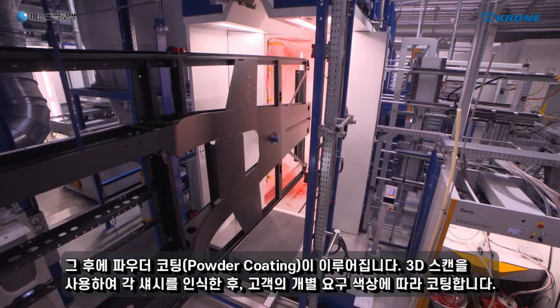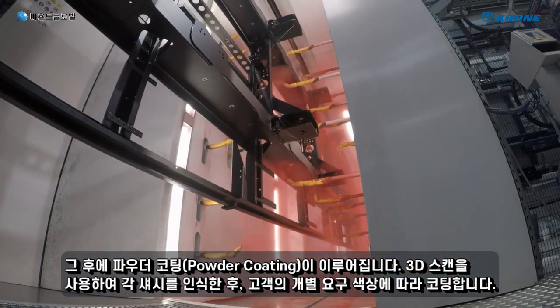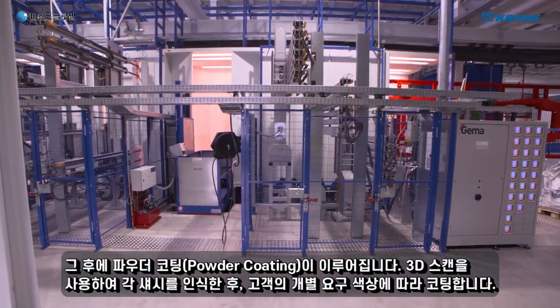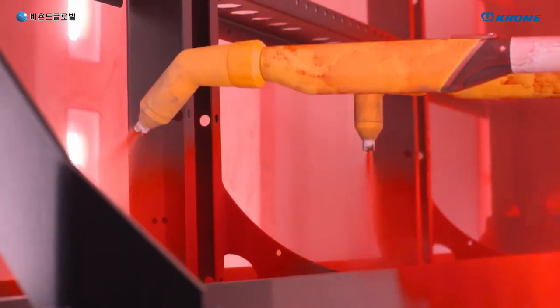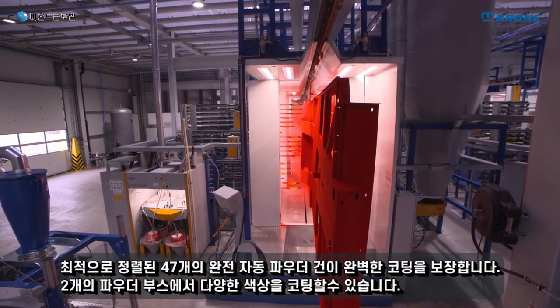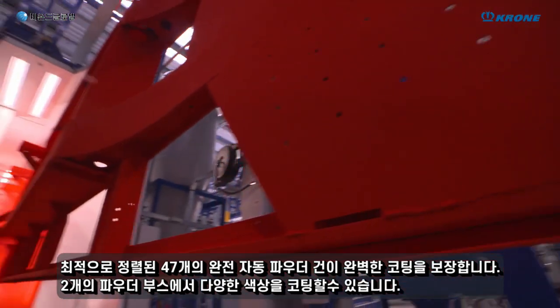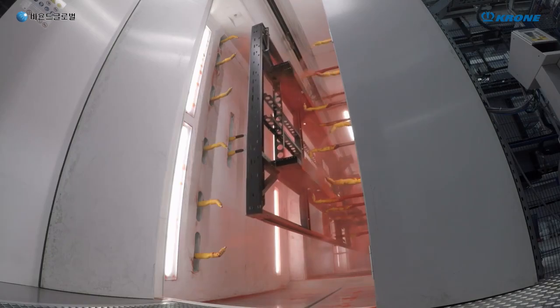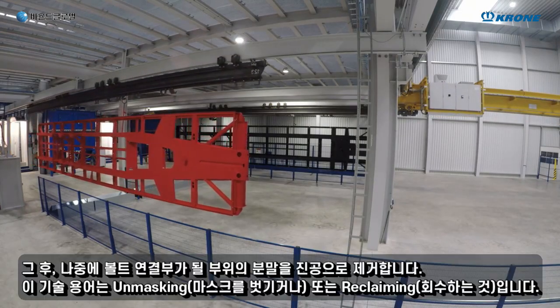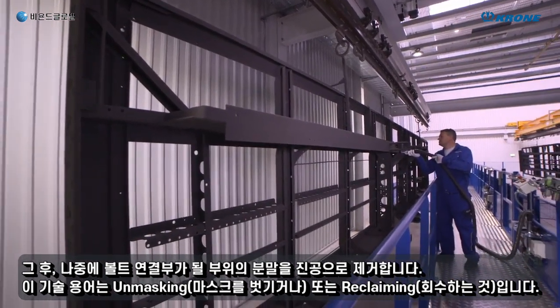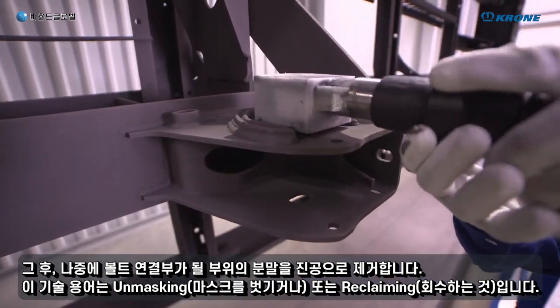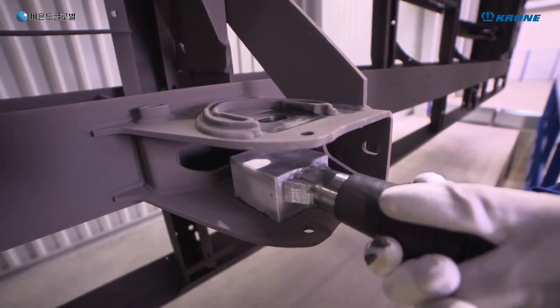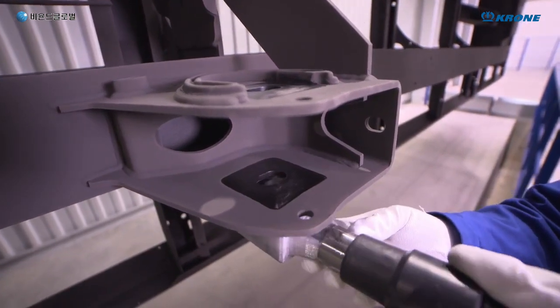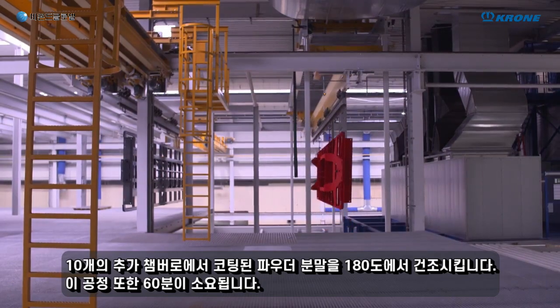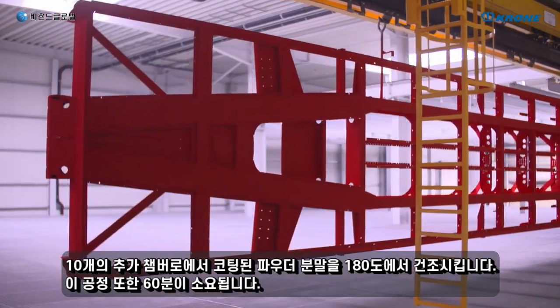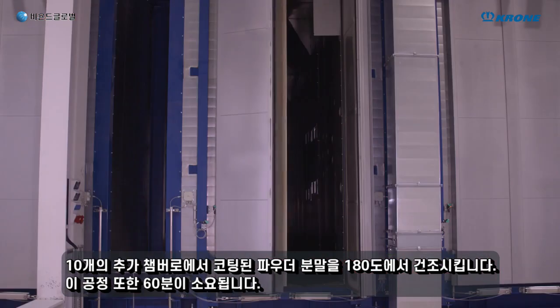Afterwards, the powder coating takes place. Using a 3D scan, the system recognizes each chassis and then coats it according to the customer's individual color requirements. 47 optimally aligned, fully automatic pistols ensure the perfect coating. Many different color tones are achieved in 2 powder booths. Afterwards, the powder is removed with a vacuum from areas where later on there will be bolted connections. The technical term for this is unmasking or reclaiming. In 10 additional chamber furnaces, the powder is then fired at 180 degrees. This also takes about 60 minutes for each chassis.